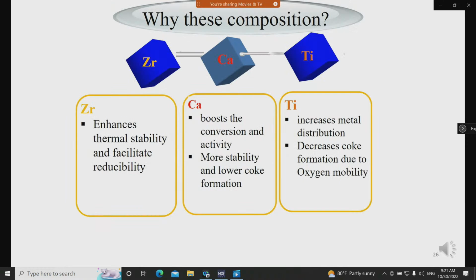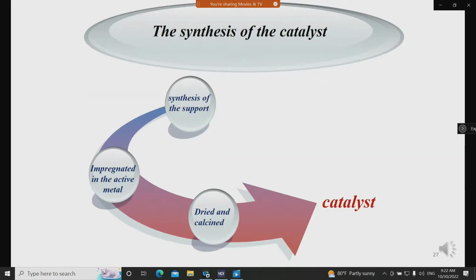And why were these compositions selected? The answer is that zirconia can enhance thermal stability and facilitate reducibility. Calcium can boost the conversion activity, so more stability and low coke formation can be expected. And titanium can increase metal distribution and also decrease coke formation due to oxygen mobility. The prepared catalyst was then dried and finally calcined.